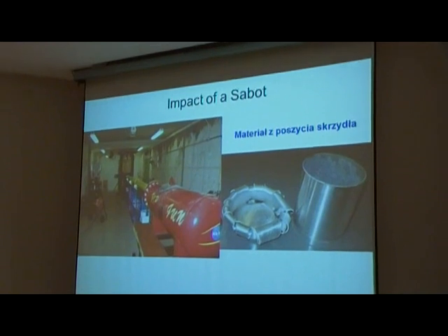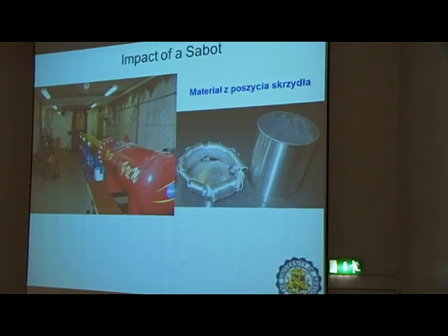Same thing for tests that are different from ballistic. And I use this material to find out if it is brittle at higher velocity. So we use a sabot, and this is our gas gun in our laboratory, and you can see the result of the impact when the projectile is accelerated in this tube and impacted into a very thick wall. So this is like a rigid wall at the speed of sound. From this you can damage this aluminum completely in that part, but there's no brittleness. The material basically is very plastic, and we can also capture this using material